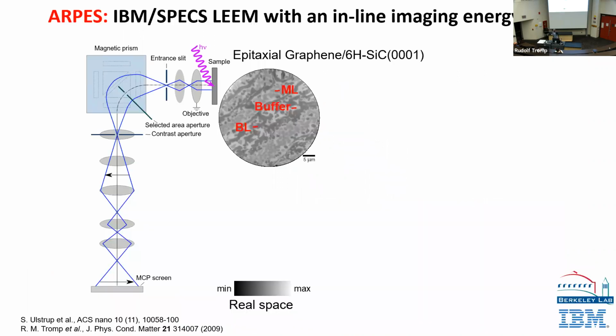I'll show experiments for graphene again. These were experiments by Søren Ulstrup at Berkeley. He uses one of our microscopes. They come in with ultraviolet light here. The sample creates photoelectrons, right? So the photons make photoelectrons. The photoelectrons come out. We take a narrow slice out of the angular distribution and then project the thing on the screen. Here's a real space image against silicon carbide with graphene on it.